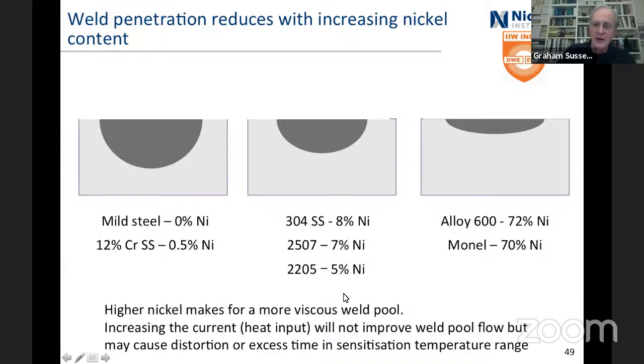But you've still got enough so the weld pool is more viscous than it is for the mild steel or the 12 chrome. And increasing the heat, increasing the current input won't improve the flow, but it may cause distortion or excess time in the sensitization, or giving you bad phases.